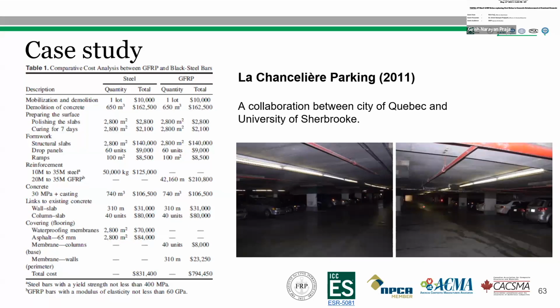If you look here, if we had used the steel reinforcement, the total cost would be around $831,400. And when using the GFRP bar, the total cost comes to around $794,450. So that is a saving of around $37,000 by building with FRP bar. Although the product they used to reinforce the concrete was twice the price of the steel, they saved money by avoiding waterproofing and installing asphalt, which is not necessary when we are using FRP reinforcement.